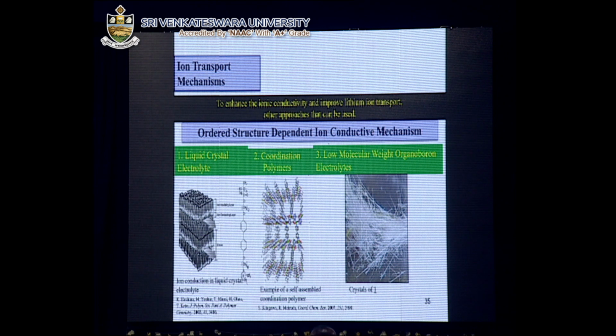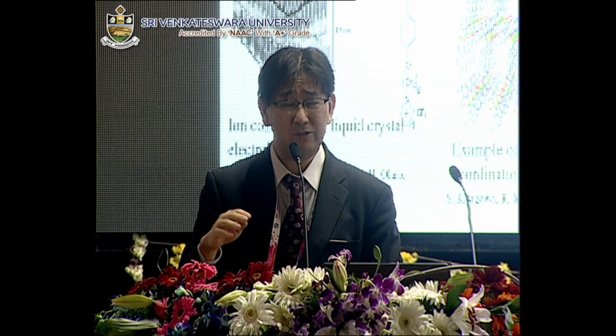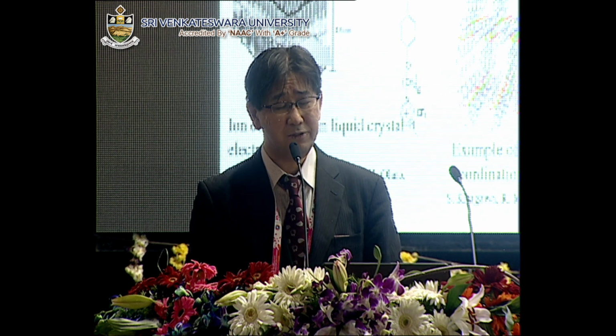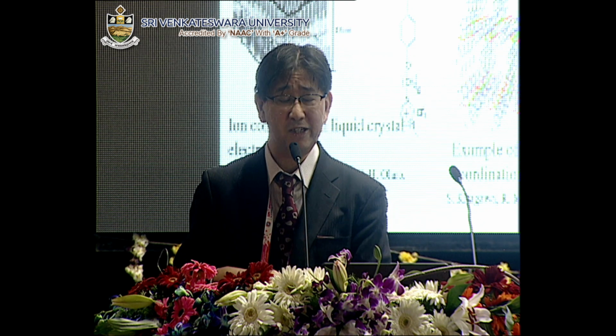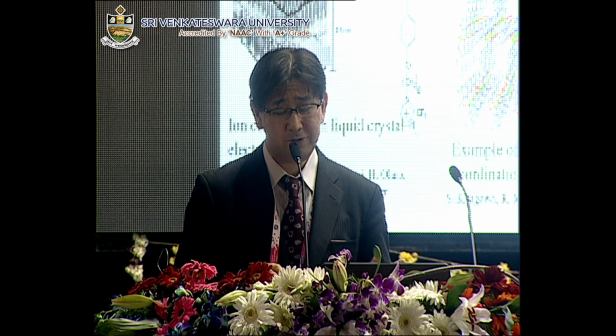For instance, some Japanese researchers tried to introduce a liquid crystalline smectic A layer to ionic liquid-based systems. And as a result of such dimensional control of ion conductive paths, a significant enhancement of conductivity has been observed. On the other hand, Kitagawa et al. reported MOF-based proton conductive channels. And now we are trying to utilize a crystalline boron compound as a scaffold for ion conductive paths through boron-anion interactions.